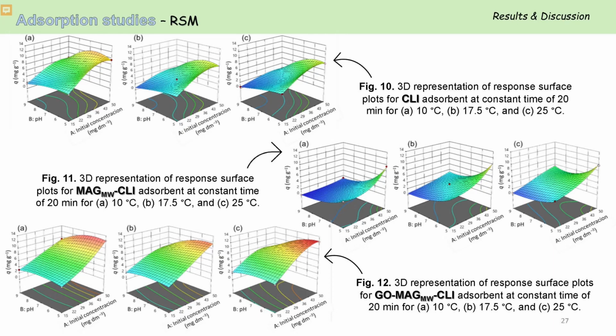The best adsorption capacity was achieved for the graphene oxide magnetite, which I can see here also according to colors. That can be attributed to the graphene oxide, because graphene oxide significantly increases the specific surface area.